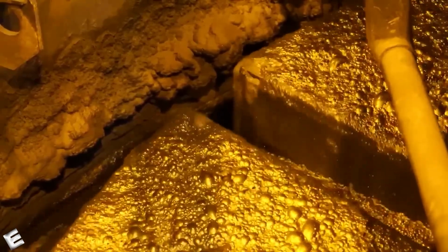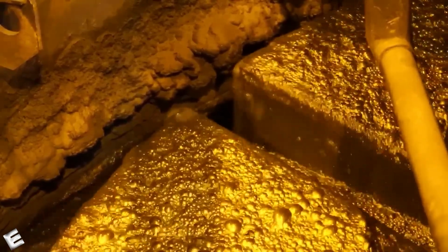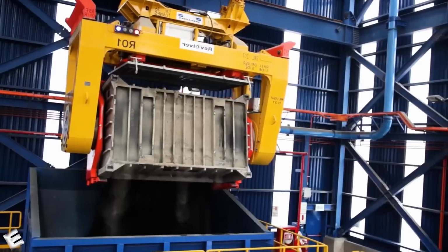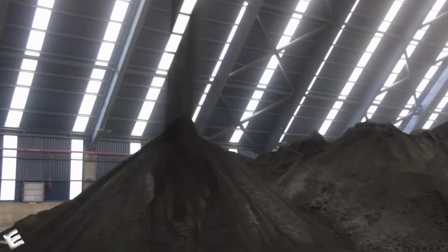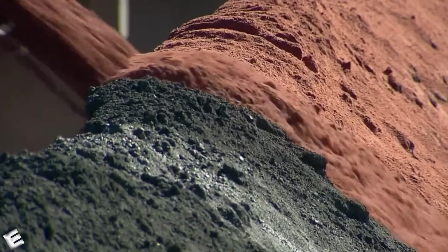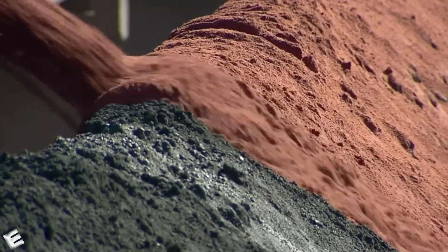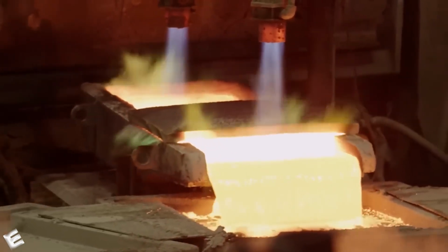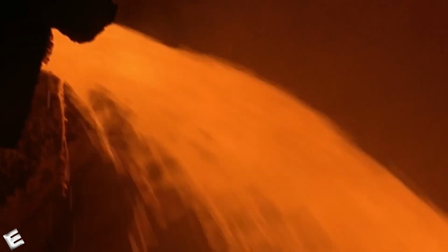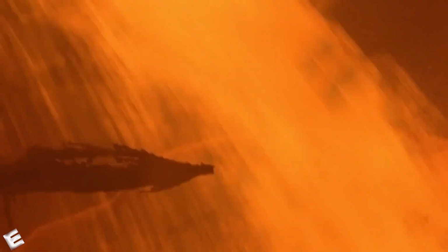The next step takes place in the smelting plant. The concentrate travels by train to enormous yards, where it is mixed in layers with silica sand, known as flux. This sand helps remove impurities during smelting. At extreme temperatures, the mixture turns into an incandescent liquid. The slag, made up of iron and other minerals, floats to the surface, while the copper sinks. At this point, the copper already reaches a purity of 60%.